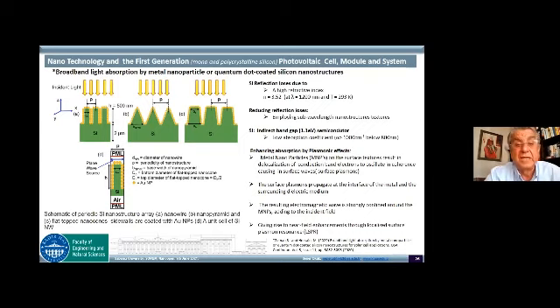Again, nanotechnology comes in here. If we introduce metal nanoparticles on those nano textured surfaces, what happens? You start with the delocalization of the conduction band electrons. They start to oscillate with the incoming waves, and surface plasmons propagate to the interface of the device, and this creates plasmon resonance, near field enhancement, which will affect your efficiency significantly. You can see how nanotechnology can help the progress of even the first generation solar cells.